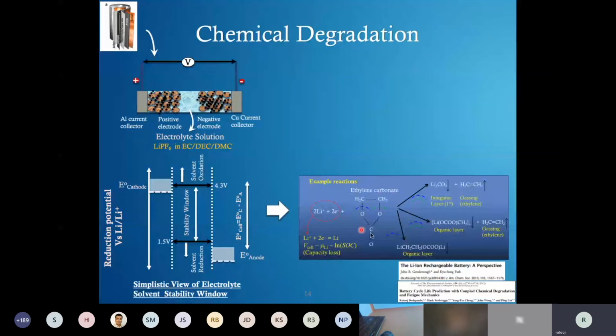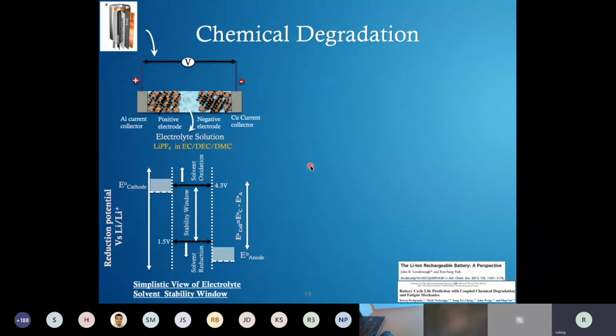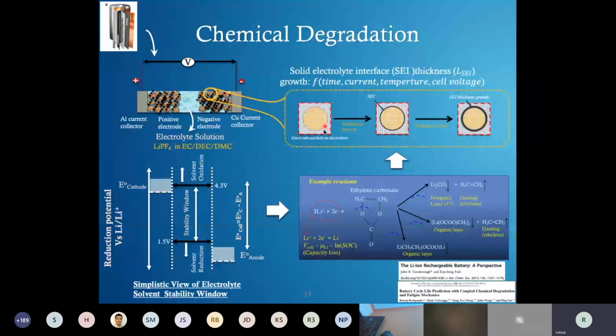The result is the electrolytes, which are carbonates, are not stable, and they decompose on the electrode surface. As soon as they see some electrode surface, they react and form inorganic compounds such as lithium carbonate, or gases such as ethylene or carbon dioxide. So various reactions happen. These are side reactions, or unwanted reactions. The result is that the electrode particle is surrounded by the electrolyte, and as soon as you form this cell, there is a layer of compounds or reduction products forming around the electrode particle. This layer is called the solid electrolyte interface, or SEI.